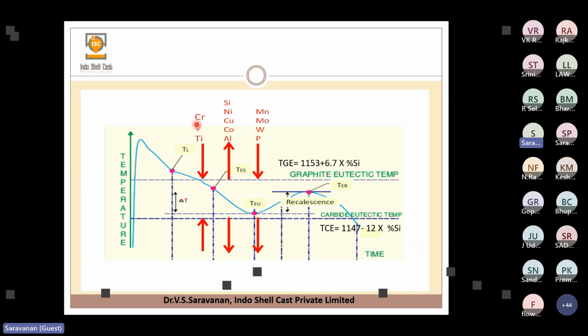Some of the elements push these boundaries, the graphite eutectic temperature line and the carbide eutectic temperature line. Here, chromium, vanadium, titanium push the lines towards each other. Then it is narrowing down, and narrowing down means automatically the delta T will go down. So this is not desirable. That is the addition of chromium, vanadium, titanium. If the content of these elements in the metal is more, then we will have problems in the metal.